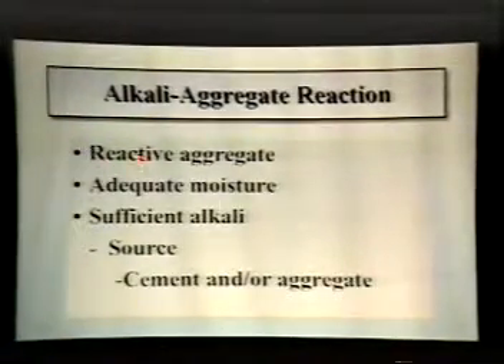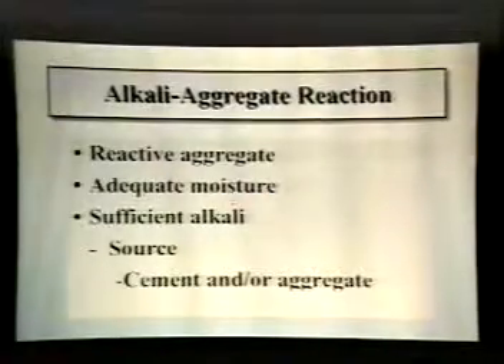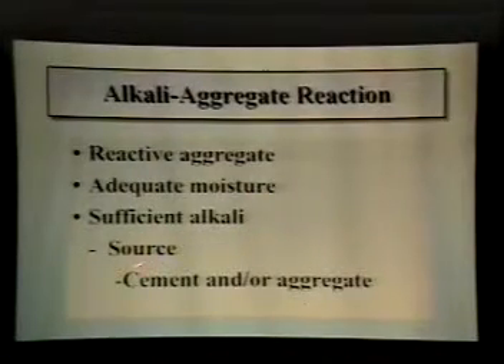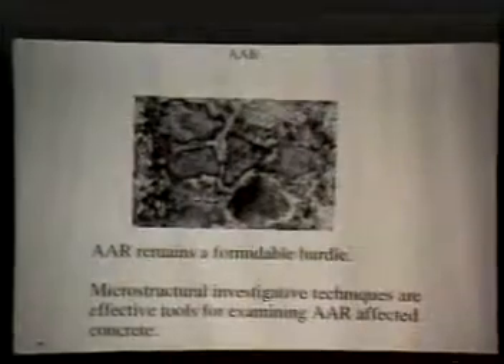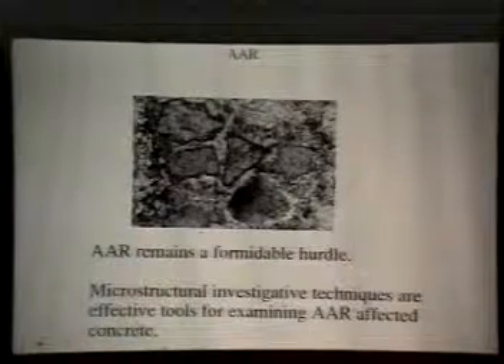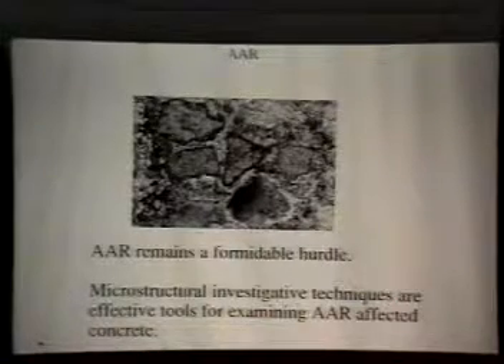Now, we found that it had the reactive aggregates. There was adequate moisture available. There were sufficient alkalis. We don't know what the source was. It could be the cement, it could be the aggregates, but there were definite signs of alkali aggregate reaction causing all the problems. One of the recommendations was to change the expansion joint, and this is the old one. This is being replaced with a newer type. This is another sign of alkali aggregate reaction where you have discoloration rims around aggregate particles. It still remains a formidable problem. And interestingly enough, microstructural investigative techniques are the most effective tools for examining AAR-affected concrete.